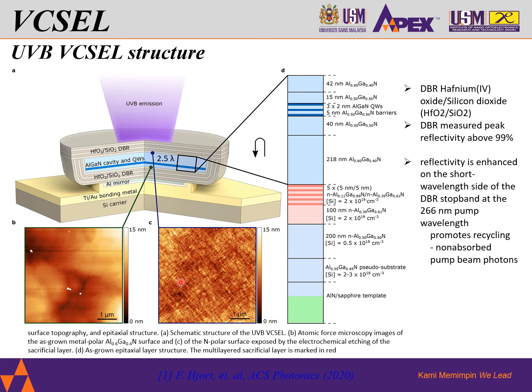create a smooth etching. The smooth etching actually was achieved by using a multi-layered sacrificial layer, which promotes etching at the sacrificial layer and cavity interface as seen here. This enables the incorporation of layers with a high aluminum content without degrading the crystal quality structure of the device layers, and the built-in polarization field yields sheets of high carrier concentrations, both of which enhance the selectivity and result in smoother surfaces.